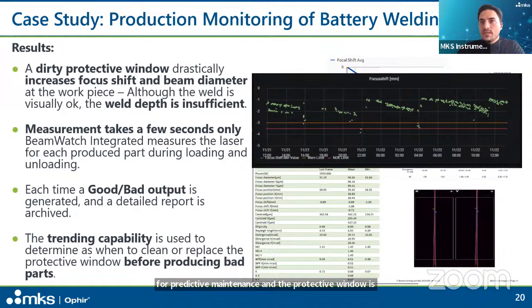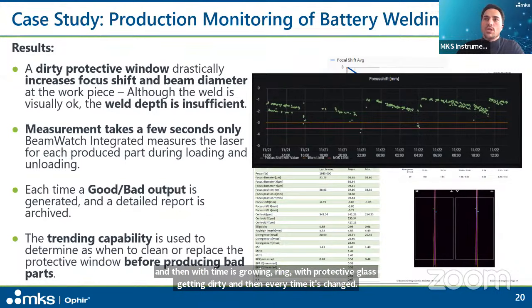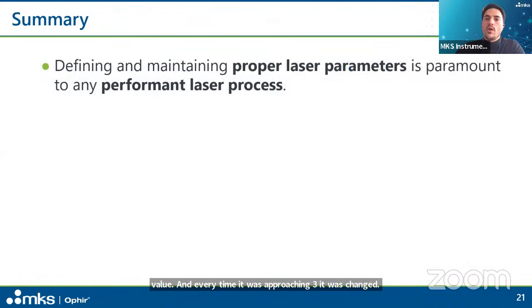What you see here is like a chainsaw, or the blade of a saw, these green dots. Every time the protective glass was replaced, you can see that the focus shift goes back down, it is smaller. And then with time, it grows as the protective glass gets dirty, and then every time it's changed. The limit here was fixed to 3 millimeters as an acceptable value, and every time it was approaching 3 millimeters, it was changed.